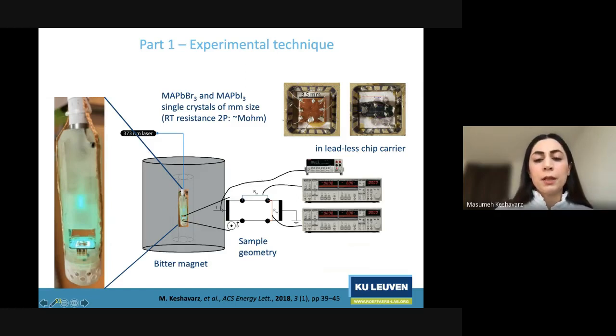And we measure the voltage perpendicular to the current, which we call RXY, and that is the Hall signal in the presence of a magnetic field. The magnetic field is always perpendicular to the plane of the sample. The current will be sent by a Keithley, and the signal will be detected through lock-in amplifiers.